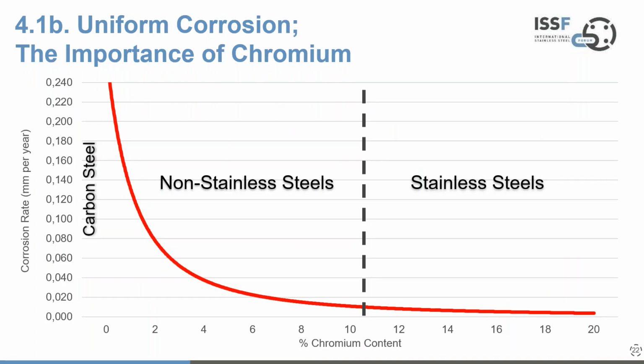So whilst we're talking uniform corrosion, I'd just like to demonstrate the importance of chromium as an alloy in materials. And on this graph, we have a corrosion rate on the y-axis on the left, expressed in millimeters per year, and then chromium content on the x-axis varying from zero right up to 20%. And we could go on if we wanted above that, but there's no real need.